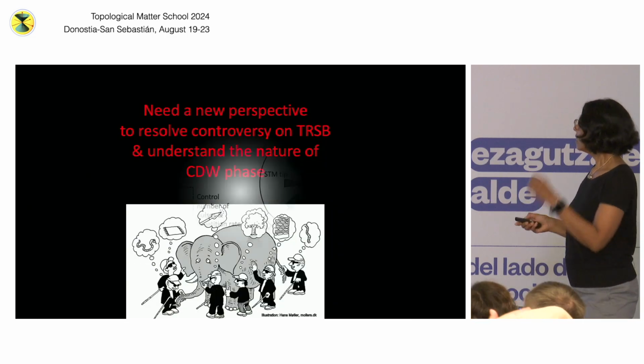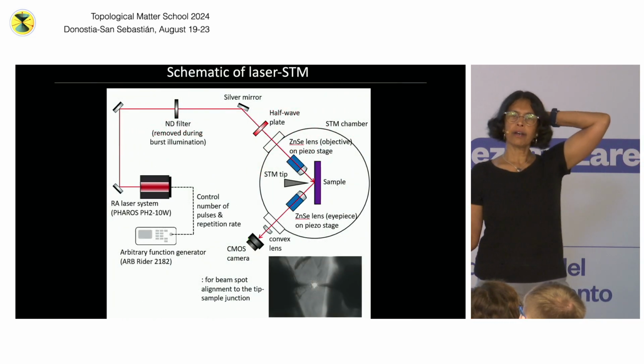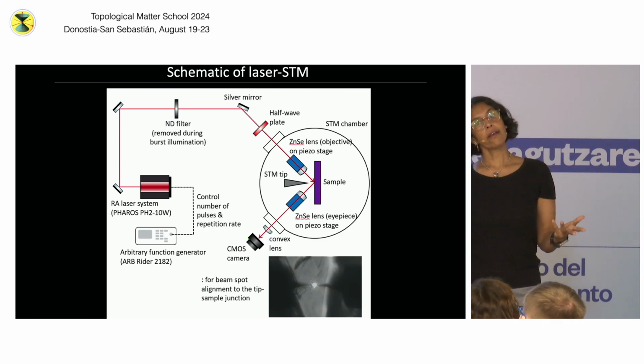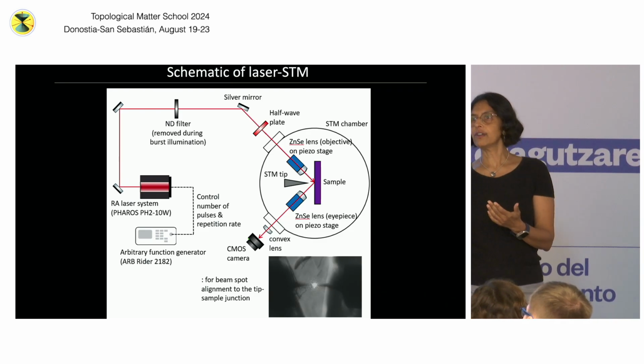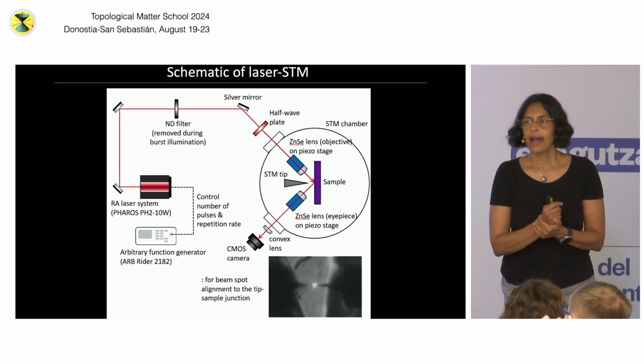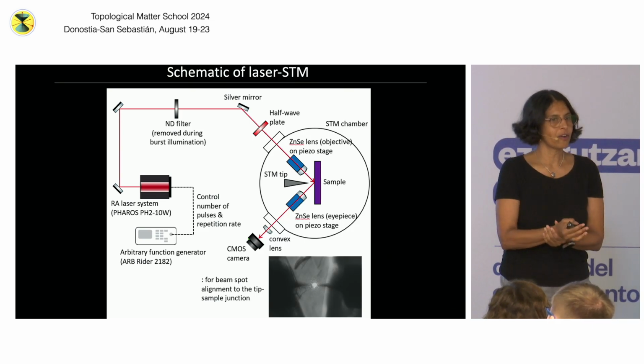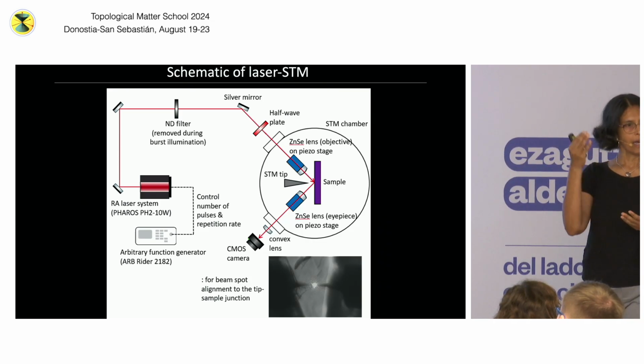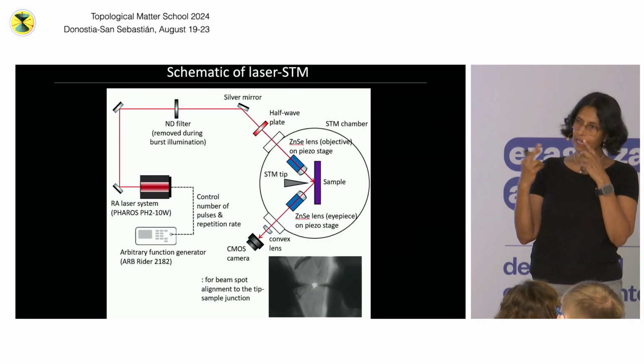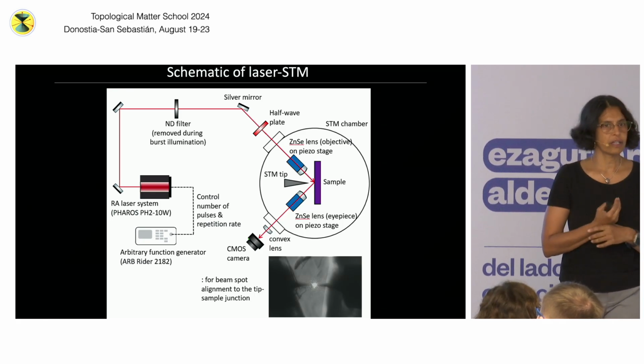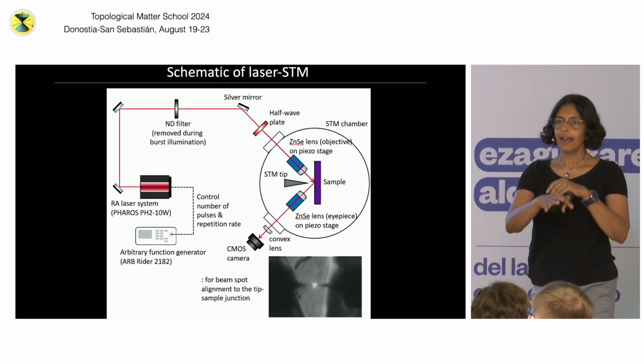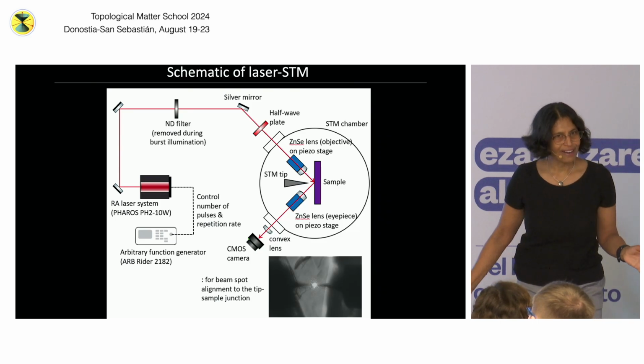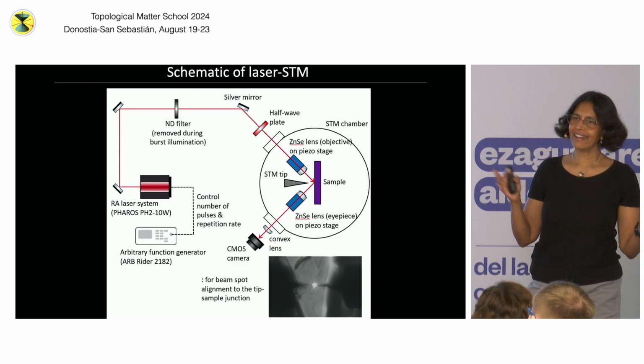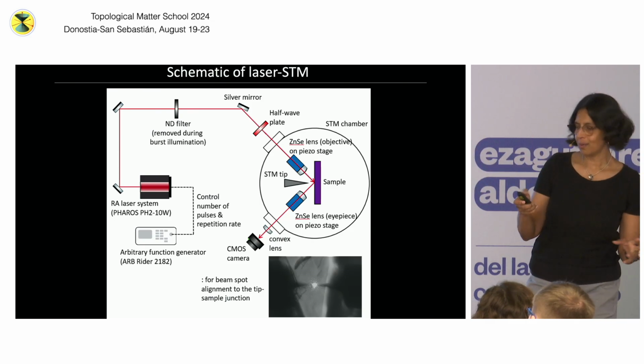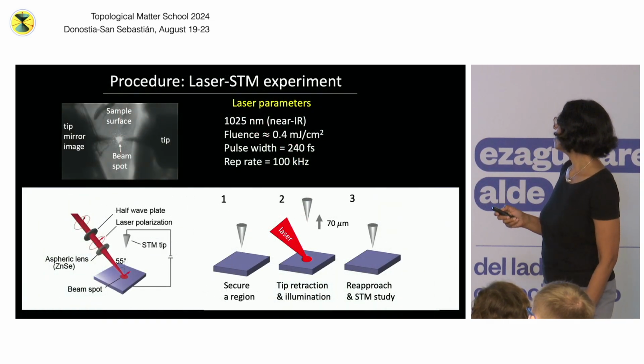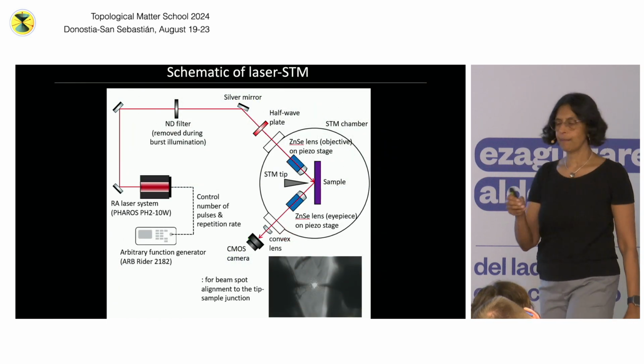So having the loop currents is actually pretty cool, and we'd like to see if this is happening in this system. Okay, so my original idea when I heard about Zahid's experiment was, okay, well, we know we can break time reversal symmetry with circularly polarized light. And so why not shine circularly polarized light on this CDW system as it goes through the transition and see if we can manipulate the order of this charge density wave with circularly polarized light. That was the original idea. It was a spectacular failure. It didn't work, right? My postdoc tried it and they couldn't see anything. It just didn't work. So then they tried linearly polarized light, and that's the data I'm about to show you.